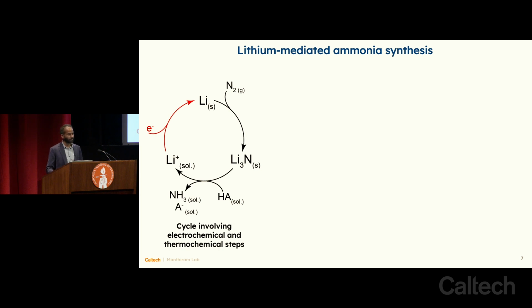And what I want to share with you today is a process whereby you can use lithium metal to actually drive this reactivity. And so here, starting with lithium metal, one can react with nitrogen. That lithium metal reacting with nitrogen can spontaneously make lithium nitride. This is one of the really special things about lithium metal, that if you expose it to nitrogen gas, it will spontaneously break the nitrogen triple bond. Even though that triple bond is so strong, in the presence of lithium metal, it dissociates and it makes a solid state form of nitrogen, here Li3N. That lithium nitride can then be protonated by a proton donor that I keep generic for now.